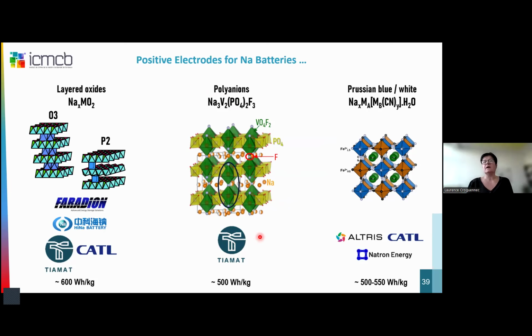It's a 3D materials. You have here this bioctahedral unit, and you have here along this bioctahedral unit fluorine, and here in the square here of these octahedra oxygen. And we can play, in fact, with the oxygen fluorine stoichiometry in these materials. You can see that other chemistry are developed, layered and Prussian blue.